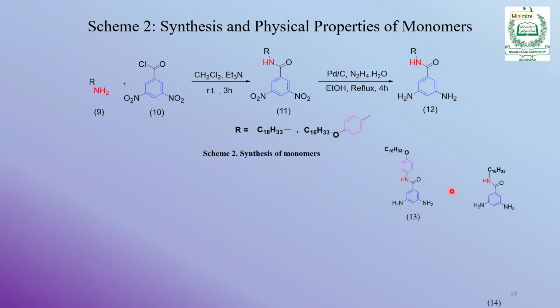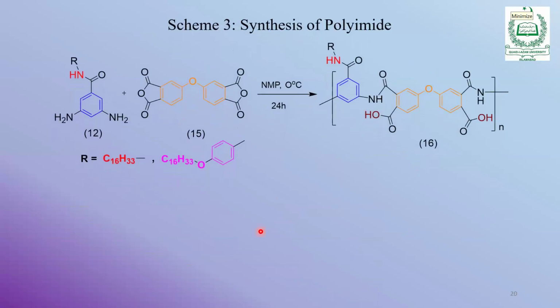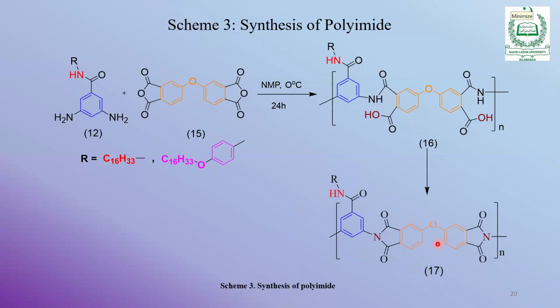So these are the structures of the two diamines, and these are the physical properties. One of the diamines was reported, the other was new. The third step was the synthesis of polymer. So we selected the oxydiphthalic anhydride and we carried out the reaction in N-methylpyrrolidone at 0 degrees C for 24 hours. This is the polyamic acid which is formed by the attack of NH2 on the dianhydride. The second step is the imidization process, which forms this tetracyclic ring, the imide section.